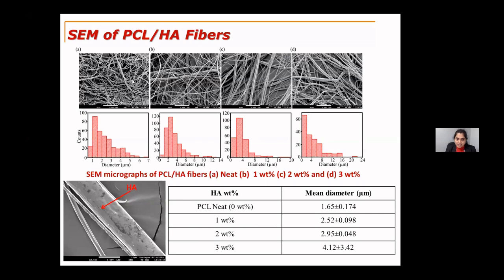As we can see here, only PCL gives a smaller diameter compared to the 1 weight%, 2 weight%, and 3 weight%. Also, the fibers are much smaller in diameter compared to the fibers infused with the nanoparticles. The neat fibers have a mean diameter of 1.65 micrometers, whereas the fibers infused with 1 weight% have 2.52 micrometers, 2 weight% have 2.95 micrometers, and 3 weight% have 4.12 micrometers.